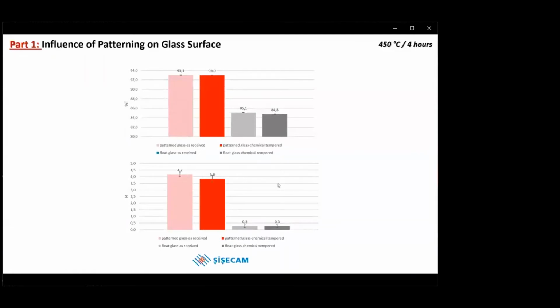When the optical transmittance and haze values before and after chemical tempering were examined, there was no significant difference between the samples. It has been observed that the decrease in the iron content in the glass composition and the application of patterns on the glass surface increased the optical transmittance values.